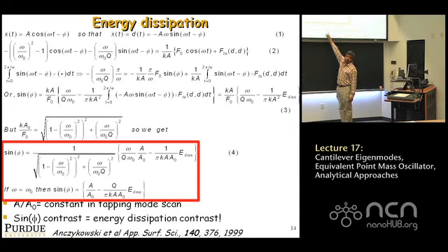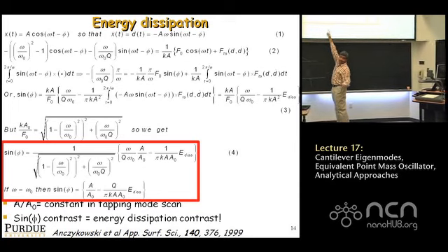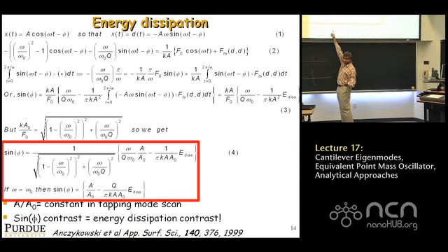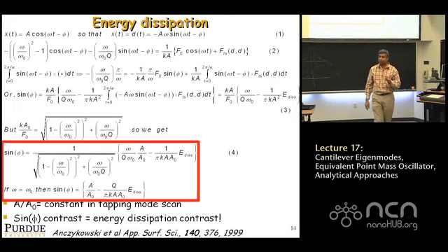Okay? Everyone with me on that? So wherever the sine of phase lag decreases, that corresponds to increased E_dis. This is why I'm saying it's extremely important that you know whether your system plots phase lag or phase lead.